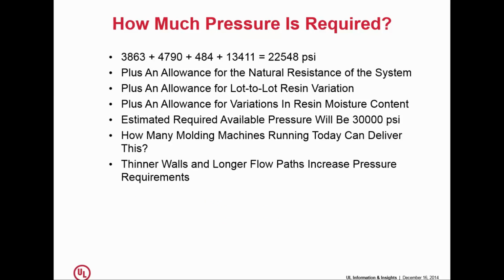Then you have to account for the fact that you're going to have lots of variability in your resins. You're going to have a variation from one batch of material to another batch of material, even if it's made within specification. Just like we have tolerances in the molding business, the resin suppliers have tolerances in their business as well. And if you're buying a 10 melt flow rate material, you might get a batch that comes in at 9 one week, and you might get a batch that comes in at 11 the next week. Well, if you develop your process with an 11, and all of a sudden one day you receive a 9, your machine's going to have to work a little bit harder to push that 9 melt flow rate material. Not a lot harder, nowhere near as much as you might think, but still there'll be a measurable difference. So there has to be some allowances for normal variation in your input of your material.